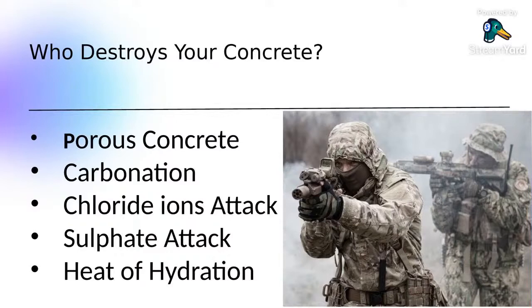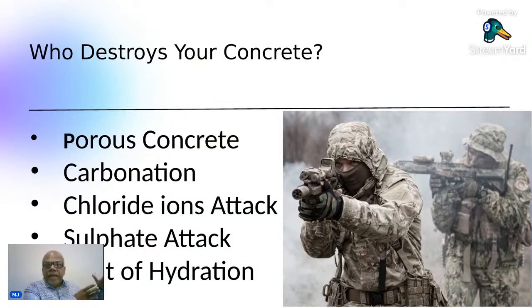Chloride ion attack. In any coastal city, we have a lot of chlorides in our groundwater, because there is salt in the sea. Salt in the sea means sodium chloride, NaCl. That chloride comes in your water, in your atmosphere, and then it attacks our concrete, causing corrosion of reinforcement. Sulfate attack. Okay, you are not in a coastal city, but probably you are in some rural India where the groundwater has a lot of sulfates in it. These sulfates attack calcium hydroxide again and form ettringite, which is huge, bulky in volume, and creates cracking in the foundation. And finally, the heat of hydration. The more tricalcium silicate, the faster the strength, but the more the heat of hydration. So calcium hydroxide is also in a way linked to it.